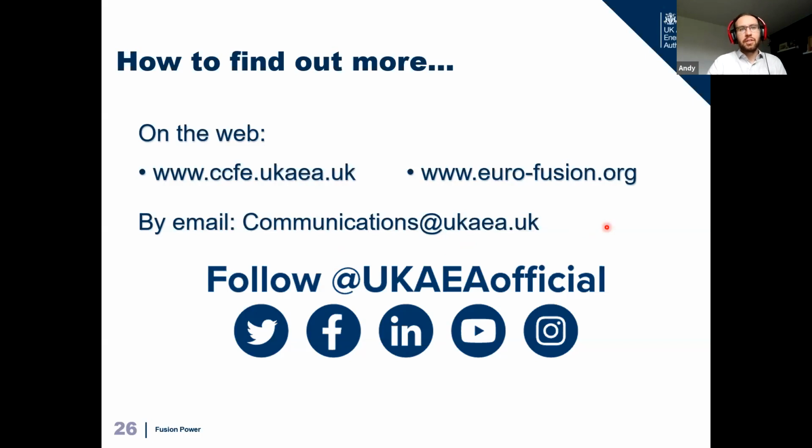Can you discuss other candidate materials for any or all of the divertor, plasma-facing components, and vacuum vessel? I don't think we have quite enough time to discuss all of the different materials. I did only focus on tungsten and steel. In terms of the divertor, tungsten is our key material because it has such a high melting point. Tungsten composites is another important one. There we're mostly looking at tungsten alloys, so adding small additions to our tungsten to improve its properties and to make it oxidation resistant, so to prevent any kind of oxidation if there was air ingress into our reactor when it was hot. That's quite important from a safety point of view.